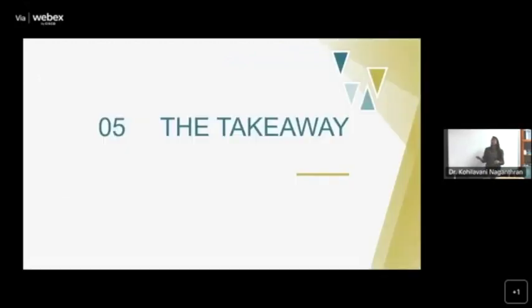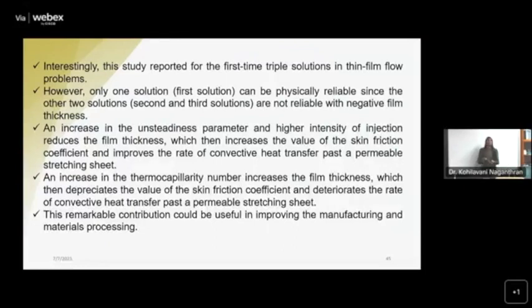The takeaway. So for the first time up to now, I guess no one presented the triple solution in the field of thin film flow, so we did. However, only the first solution we call physically reliable, and the second and third solutions are not reliable because of the negative film thickness. Because when we got the negative film thickness, it means that the coating, right, the liquid film already touched the surface.